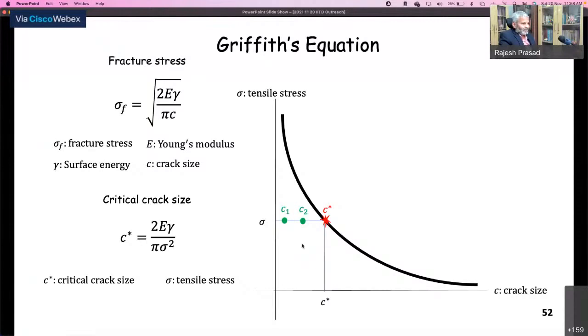But imagine if the crack size you have is greater than C star and you are loading the material with this stress, then this crack will propagate, and it will cause fracture and failure. So C greater than C star is bad news, a disaster, the bursting of the balloon. C less than C star is on the safe side, and designers want to live in this region. So this is a very, very important development in engineering science.